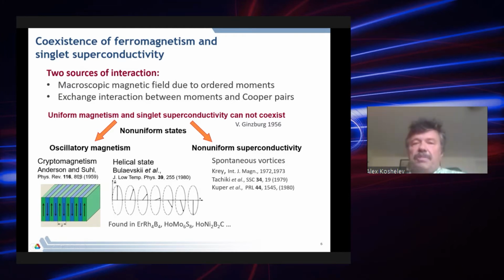The first such non-uniform state was suggested in the classical papers of Anderson and Suhl. They proposed that the magnet should split into small domains. This state is the so-called cryptomagnetism, and the size of the domains is determined by the interplay between magnetic energy and superconducting energy. This state exists when magnetic anisotropy is high, and when the magnet is almost isotropic, it was proposed that a helical state is more energetically favorable. And if the magnet is hard and this deformation costs a lot of energy, the superconducting state may become inhomogeneous instead, namely, the magnet just generates a spontaneous vortex state in zero external magnetic field. This was also proposed a long time ago.